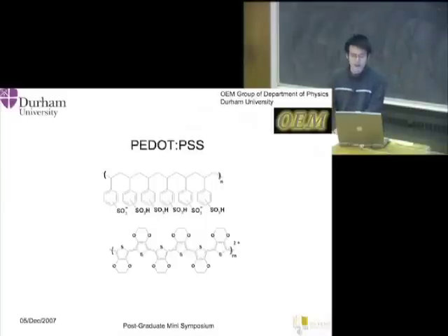And this is something called PEDOT. This is what is used as the hole injecting layer in the device, because people mostly use indium tin oxide, ITO, as the transparent anode. This kind of material has a very rough surface, so the PEDOT is spin coated on the anode to smooth the surface.